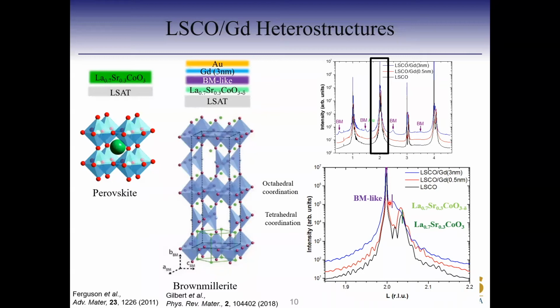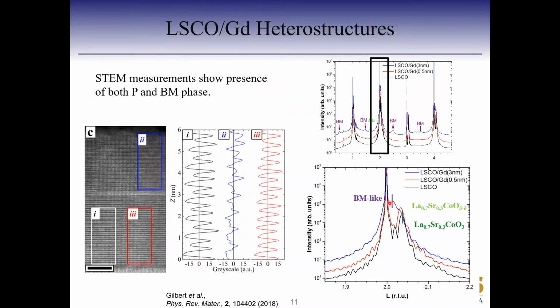Okay, and you can image it using TEM too. You can image the cross-section of these materials using scanning transmission electron microscopy, which shows the presence of both perovskite and the brownmillerite phase. So here, if you look at the red box, you have a very nice contrast and oscillations. So that's the perovskite structure. And then if you look at the white and the blue, especially the blue, you get this quadrupling structure, and that denotes that you're converting into the brownmillerite phase.